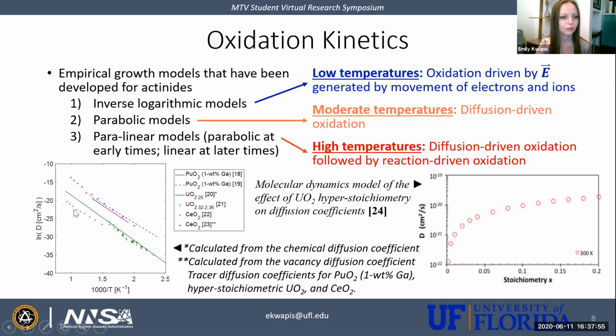And I do want to note that this disagreement between different cerium oxide data, that's very common to find in literature. There's a lot of disagreement, and I'll go into reasons for that later when I'm going through my results. But what I want to note on this slide right now is that diffusion coefficients are also a function of stoichiometry. So this had to be considered with hyperstoichiometric uranium oxide, because it wasn't a stoichiometric oxide.